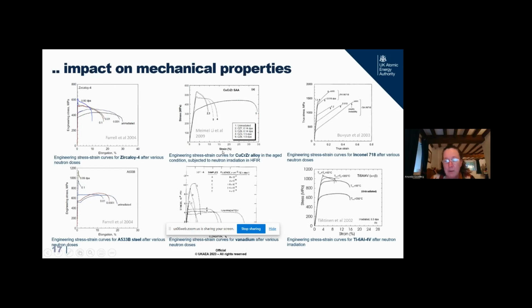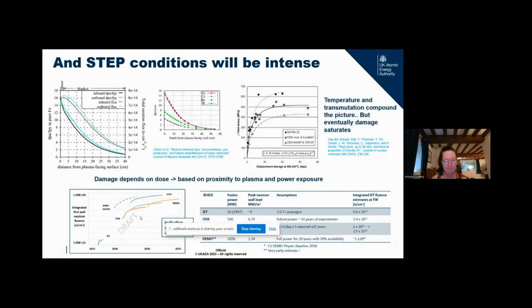But after we've applied a little bit of fusion damage, and we measure it as displacements per atom, DPA is the metric, even these low levels of DPA considerably reduce the performance at a mechanical level of what we hope will be standard building blocks in the tokamak. And you can see the pattern is the same across all of the pictures. So we see even after a couple of days of full power on STEP, we anticipate major modification of the engineering performance or behavior of our materials.